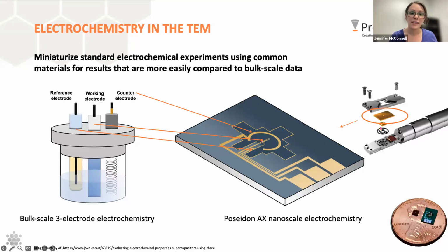And so this is then assembled in the holder as the top chip. We put all the electrodes on the top chip so that you can do excellent work in STEM. It's optimized for collecting X-rays for EDS, so you can get nice fast maps. If you're curious about why it's critical to have the electrodes on the top chip to do those things, we're happy to talk to you, but I'm not going to dive into it here. Just know this is optimized to do STEM. You can control your dose much better in STEM, as well as EDS with pretty much any EDS configuration that you have.